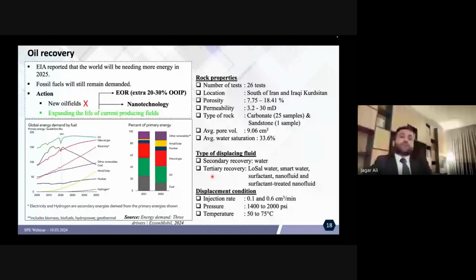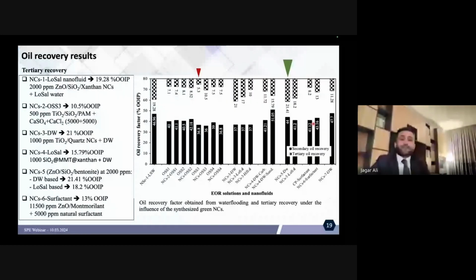So in this project, we did 26 core flooding tests. We used different types of core plugs. 25 of them were carbonate and one of them sandstone. The average pore volume of the core plugs that we prepared is about 9 cubic centimeter, the permeability varied between 3.2 to 30 millidarcy, and the porosity between 7 to 18.4. The injection rate of displacement varied from 0.1 to 0.6 cubic centimeter per minute, the pressure ranged between 1,400 to 2,000 psi, and the temperature varied between 50 to 75 degrees Celsius.